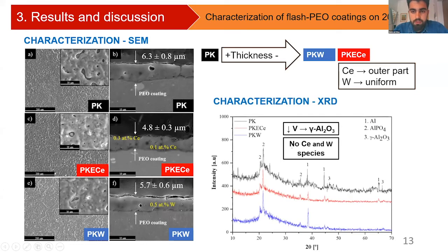And the X-ray diffraction patterns reveal the formation of gamma alumina as the most predominant phase, probably as a consequence of the low voltage used in the present work. And no cerium and tungsten species were detected in these X-ray diffraction patterns, probably due to their low concentration in the electrolyte.